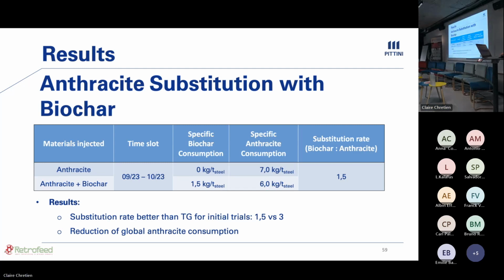These are the biochar results, of course. And we had several trials in these 2 months. And we can see that we also lowered the consumption of the anthracite compared to the tire grains. So as I mentioned before, we pay more attention to this aspect. And of course, we had trials with biochar with a substitution ratio of 1.5.